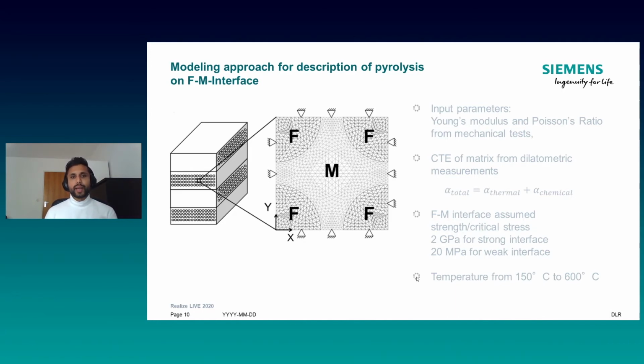And this is in comparison with the matrix strength, right? In this case, in the weak interface, the interface strength is 5 times lower than the matrix strength, and in the strong interface, it is 5 times higher than the matrix strength. And we model the complete microstructure, which we have shown here, and increase the temperature from 150 degrees Celsius to 600 degrees Celsius.